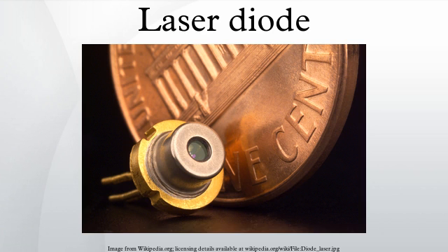In the 1970s, this problem, which is particularly nettlesome for GaAs-based lasers emitting between 0.630 micrometer and 1 micrometer wavelengths, was identified. Michael Ettenberg, a researcher and later vice president at RCA Laboratories' David Sarnoff Research Center in Princeton, New Jersey, devised a solution. A thin layer of aluminum oxide was deposited on the facet. If the aluminum oxide thickness is chosen correctly, it functions as an anti-reflective coating, reducing reflection at the surface. This alleviated the heating and COD at the facet.